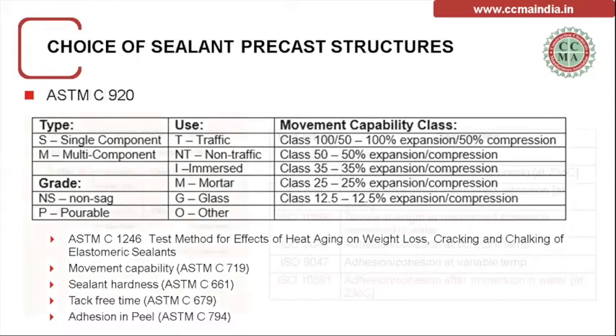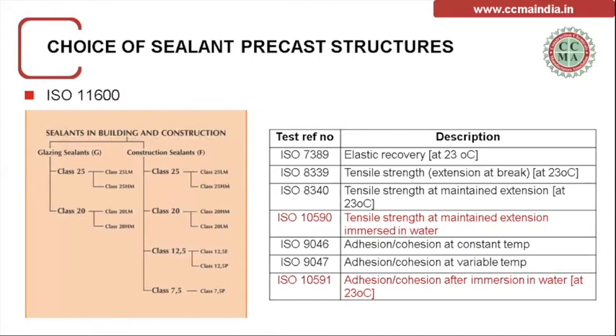But a similar standard, when we see ISO 11600, according to the classification, the most important and critical thing which the ISO classification very clearly states is that tensile strength is maintained when it is exposed to water, whether it's continuous rain for three months, two months, or immersed under water. The sealant tensile strength should be maintained. At the same time, adhesion should never get affected by exposure to this water. So it is always good to get these two qualified, specifically when we go for the joints treatment in precast structures.